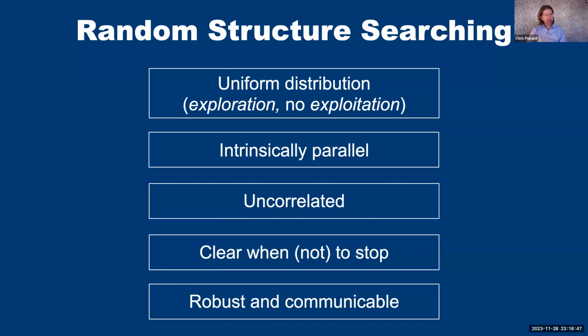So the other feature I think that's quite strong about random structure searching is that it's incredibly straightforward. The number of parameters that you need to explain or communicate to a reader or someone that you're training is very, very minimal, and they're easy to communicate. So when you're doing a random structure search, of course, you have to choose roughly the right volume or density of your system. You might put some distance constraints so atoms don't fall on top of each other. You might exploit symmetry or structural units.